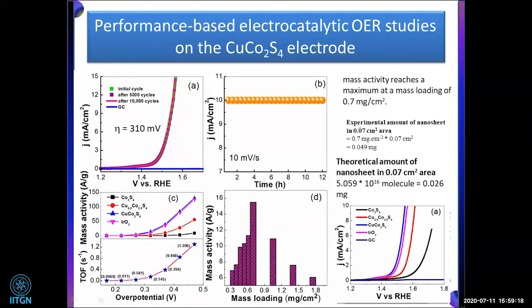So why is it important, that 0.7 milligram per centimeter square? When we did a theoretical calculation of the amount of nanosheets needed to cover the glassy carbon electrode, it actually required 0.026 milligram. And when we calculated ours, we found that the mass covering, including the binder, is 0.049 milligram. So the weight of the binder is also included. That means it is almost equal to the theoretical amount. That means a monolayer of our nanosheets is enough to cover the entire electrode surface, and that is good for the electrocatalytic reaction.